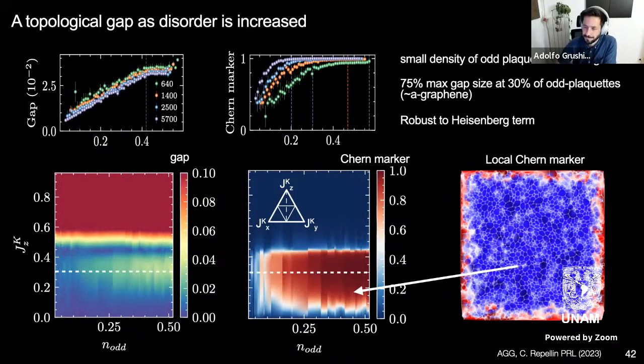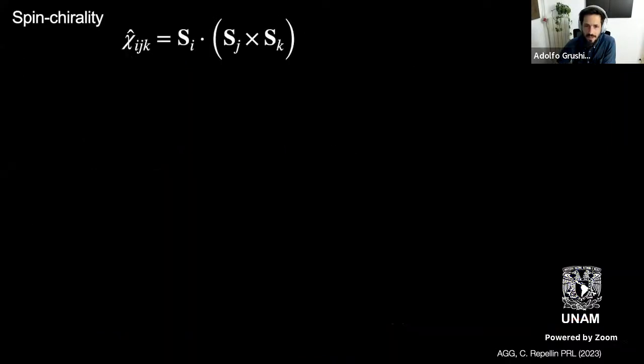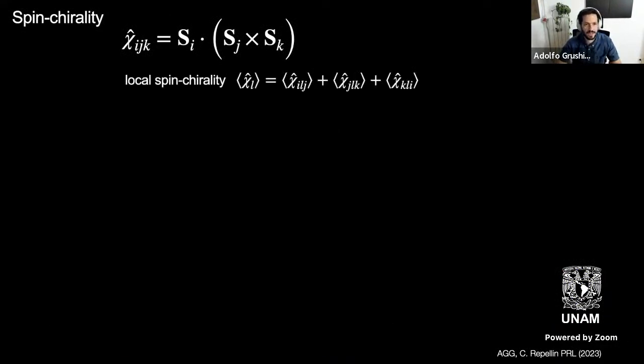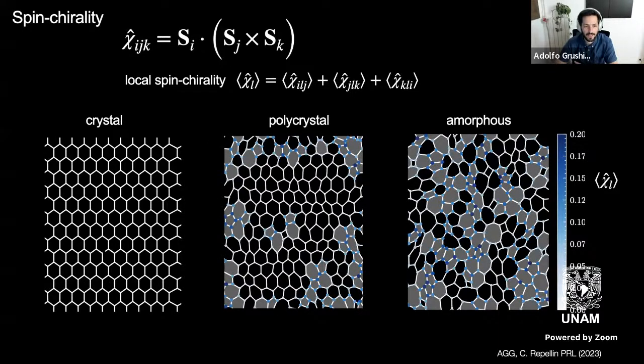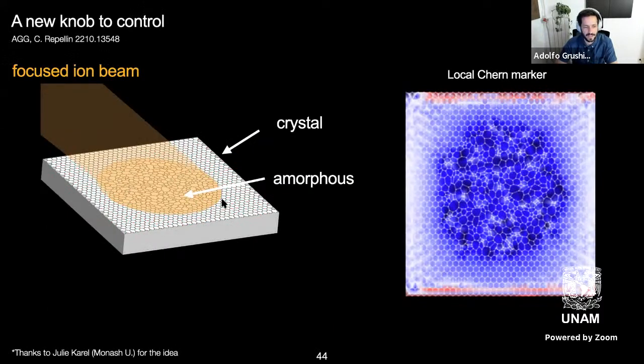And we also added extra interactions like the Heisenberg term to see whether it was robust, and indeed it's as robust as the gapless state actually, which is kind of interesting. And just to show you a little bit more evidence that this really is tied to the odd plaquettes, we calculated the spin chirality, which is an order parameter for this phase that you can make local. You'll see that for the crystal, it's essentially 0. And then as you increase the number of odd-sided plaquettes, you'll find that the spin chirality is essentially only peaked at those places where the odd plaquettes live.